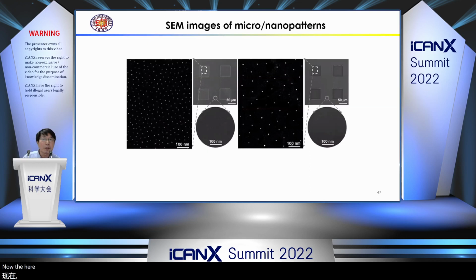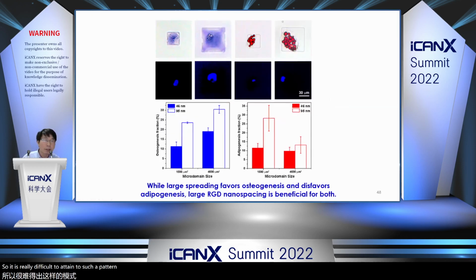Now, here is a demonstration of our pattern. You can see the micro pattern. You can also see the micro island. We can magnify it to see the nano pattern. So it is really difficult to obtain such a pattern. And we also culture cells, because due to our careful design of the size of the nano dot and also the size of the cell adhesive microisland, we can achieve single cell adhesion. We can control the cell spreading area, so we can examine the differentiation effect along with both the microdomain size and also the nanospacing.